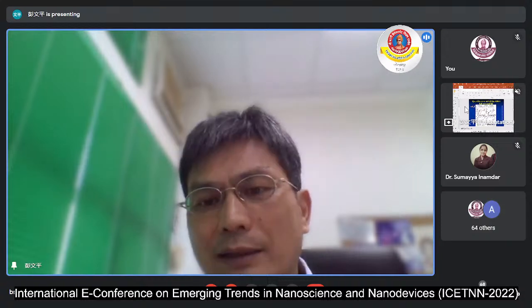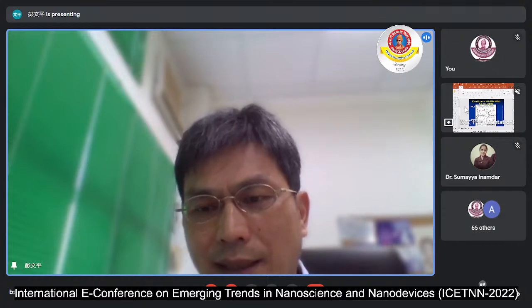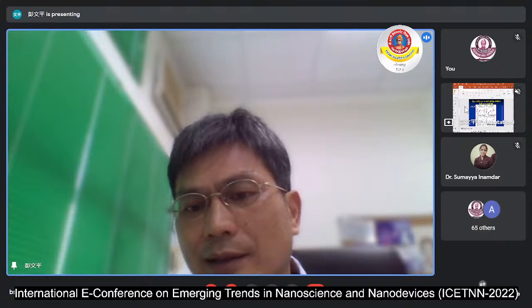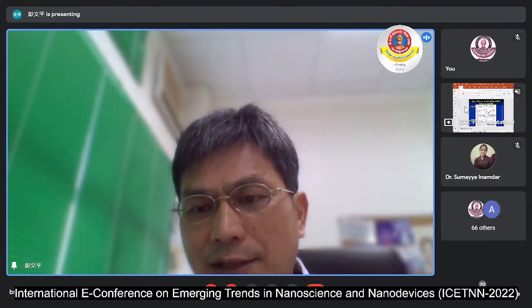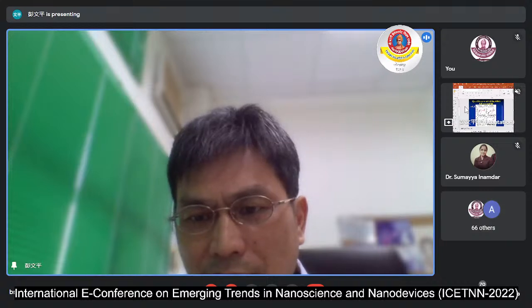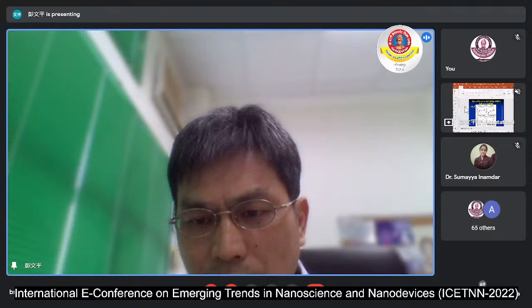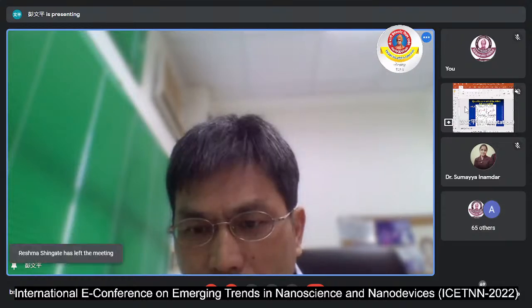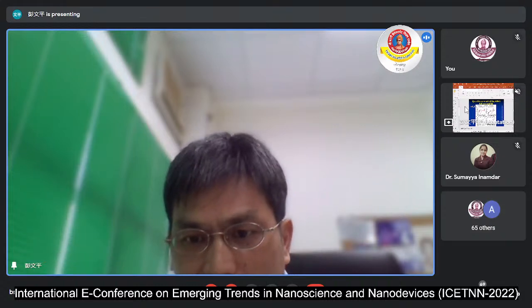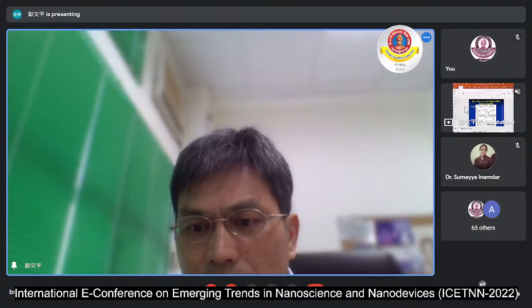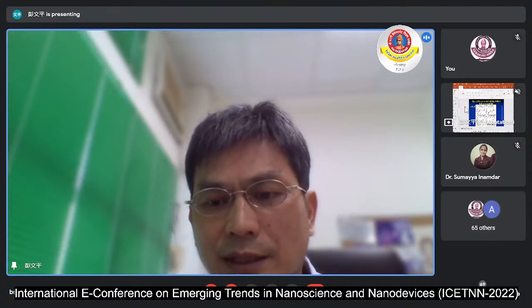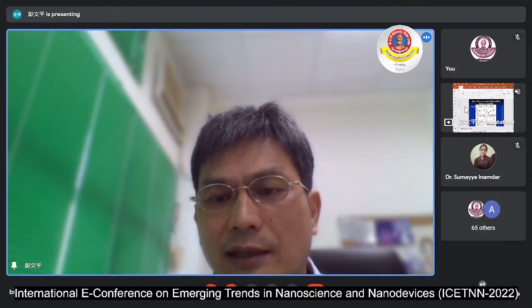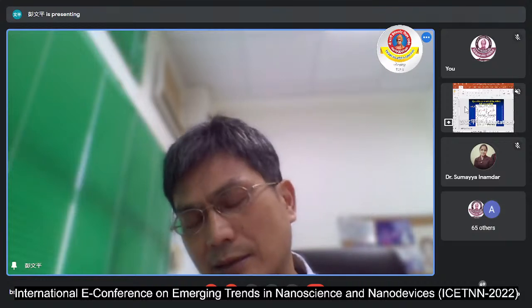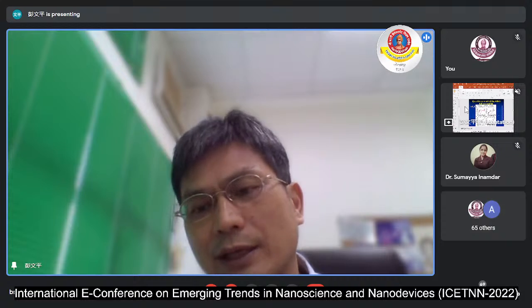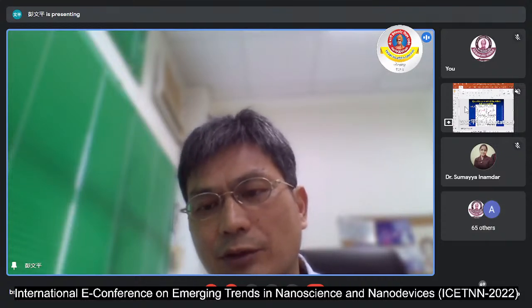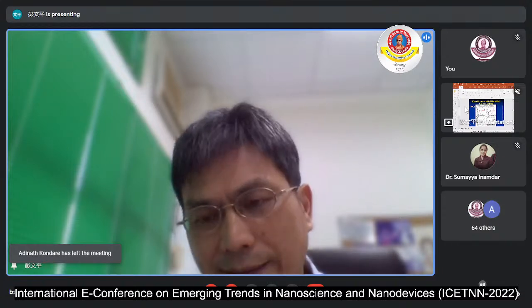So we plot the Langmuir plot, then we fit the curve and the Langmuir isotherm. As you can see here, for HPHT nanodiamond it is around 10 to 13. For particles, you can observe the linear part of this Langmuir isotherm. We know the linear part of the Langmuir isotherm is useful, so based on this curve we can calculate how many particles will absorb and form the monolayer.